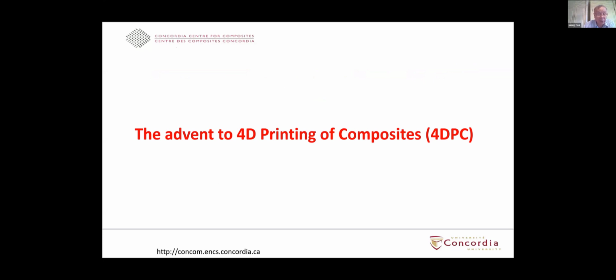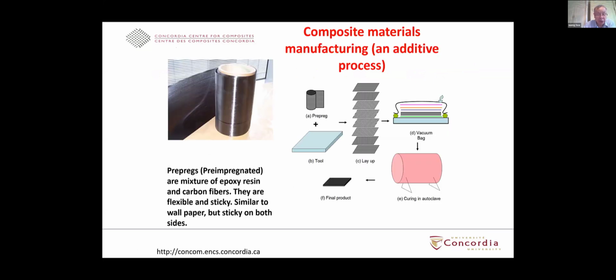So we talked about the 4D printing of composite. We started working with the 4D printing of composite over the last few years, and we have made a few things. I think I have probably presented this to some of the people here before. The way that people manufacture composite material is that you use something we call a pre-preg. The pre-preg has the carbon fiber embedded inside the epoxy resin. You cut the pre-preg into different sheets and you can lay them up into different orientations, like 0, 90, 45, and so on. Then after that, you put that inside an oven or autoclave to cure and you get a piece. So basically that is the conventional way of doing composite manufacturing.